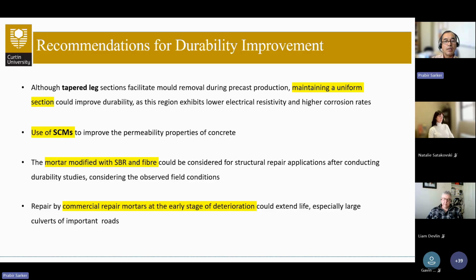We have seen that these supplementary cementitious materials, for concrete subjected to accelerated curing, improved the permeability and the chloride diffusion. That is probably not used as much currently in the production of the culvert, so that can also be considered to improve the material properties of the concrete, which may improve the durability of the culverts.